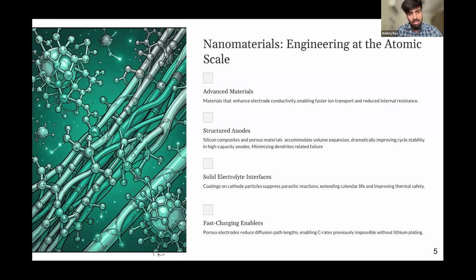Number 4 is fast charging enablers. Like we mentioned, we need to replace petrol, right? So we need to have charging which can happen in less than 10 minutes. So the porosity of electrodes is very important over here, which reduces the diffusion path length of the lithium into the anode material.